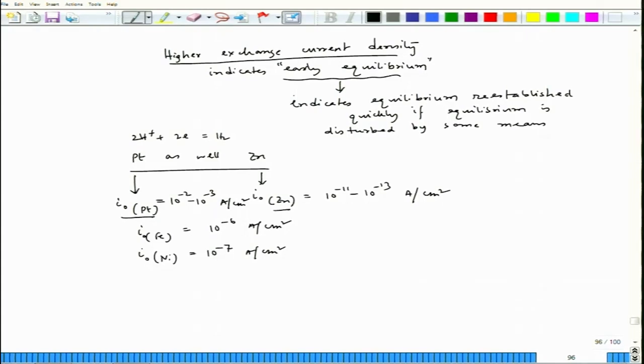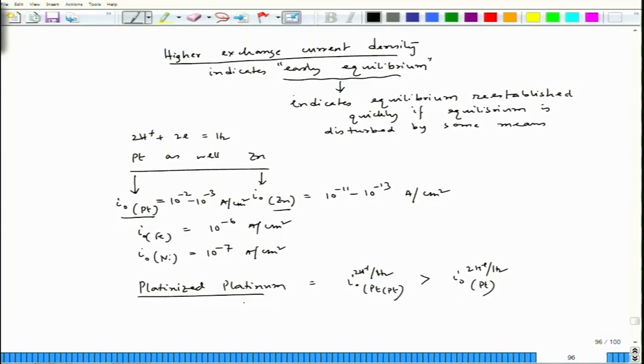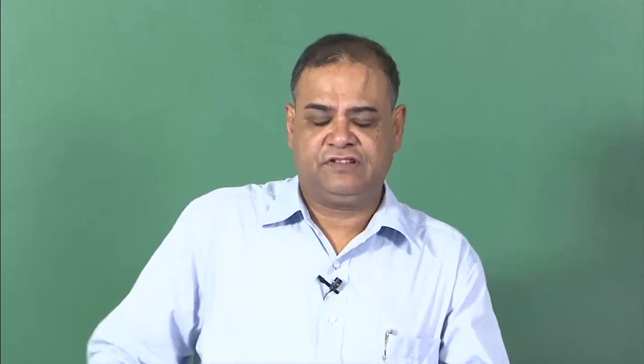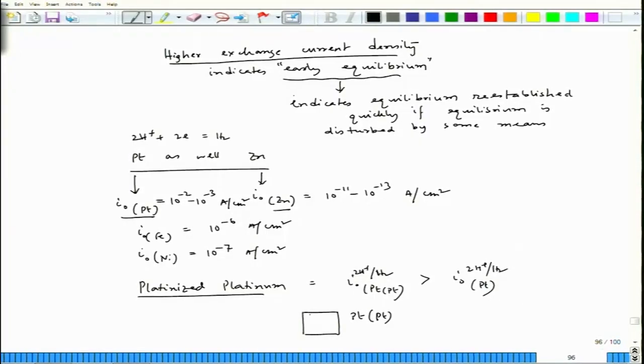Now, instead, sometimes we use platinized platinum. And in case of platinized platinum, I 0 for this hydrogen reaction is much higher than I 0 on platinum. See, when it is platinized, on platinum, platinum is plated. So, when platinum is plated, it actually forms a very rough surface. And it means that if we have a particular area of platinum, and if it is platinized platinum, then the actual area increases. If we see this from the cross section, it would look like this. So, this is the cross section from the side if you look at it.